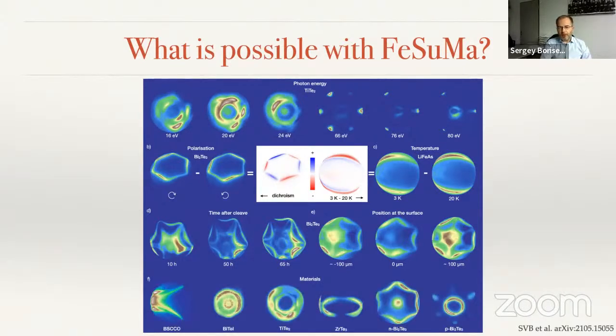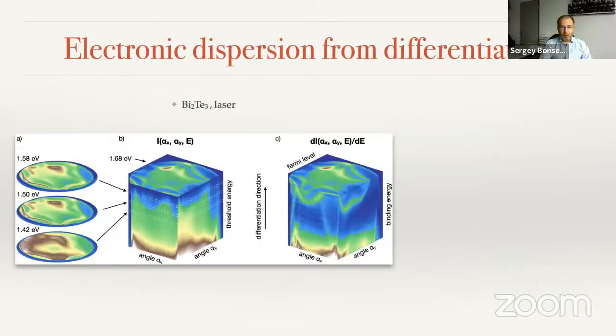Finally, you can do the measurements of different Fermi surfaces for the different materials. This is obvious. Not only momentum distribution can be recorded, one could do the energy direction as well. But one needs one additional step, a differentiation, because when you set the threshold energy at the detector, you're collecting electrons having energies above these threshold energies. It means that if you're interested in the momentum distribution of these electrons as a function of binding energy, you could reduce this threshold energy and then record the integrated spectrum.